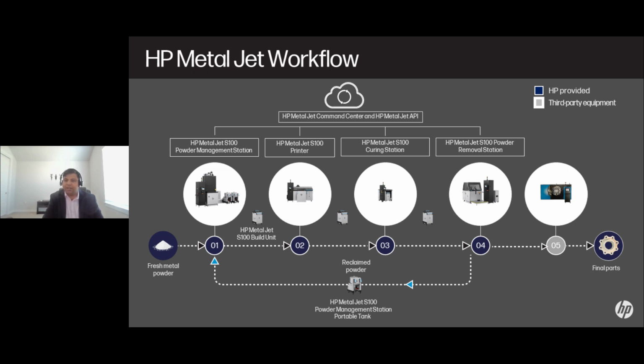In the printer, the farther end build boxes containing powder rise layer by layer, and each layer thickness varies from 30 microns to 70 microns, or up to 90 microns, depending on your needs. A roller spreads a thin layer of powder. On top of it, a printhead deposits the binder in selected locations. Imagine it is like printing on a piece of paper at home, except you're printing on a metal powder bed. You continue this process layer upon layer until you get a final 3-dimensional part. What you did here is basically gluing metal powders together in the form of a 3-dimensional shape.